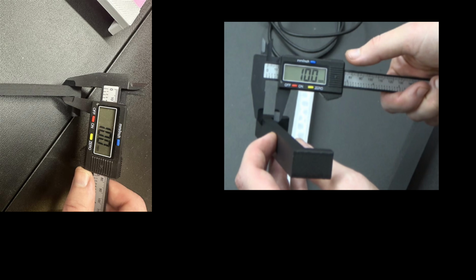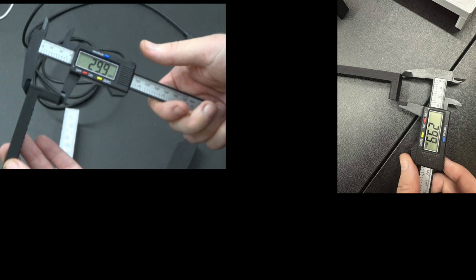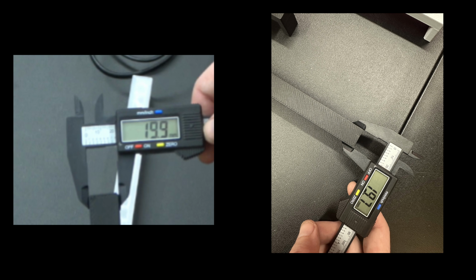Okay, so checking out the measurements, looks like the 10.0 measurement stayed exactly the same. The same thing can be said for the z-axis at 29.9 millimeters. However, as far as the width of the actual object, it does look like we shrunk about 0.2 millimeters. So during the annealing process, there was at least a little bit of shrinkage going on, as well as the part started to warp just a little bit. It looks like it started to curl up. And so I will show you what I mean here.